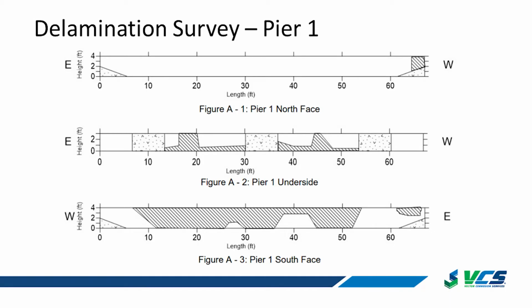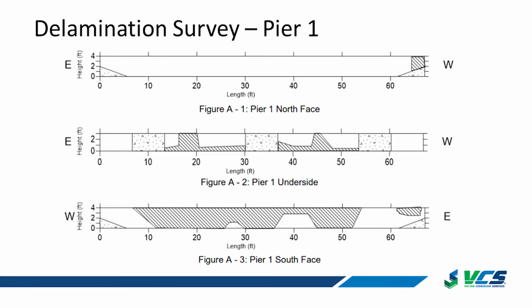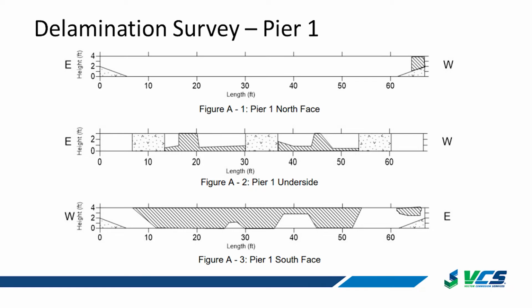We also did a delamination survey, right? That's kind of the big key here: did the system work or not? What are the current delaminations in 2020, when we were out there? Was there more delamination on Piers 1 and 2 versus 3 or 4, or was it relatively the same? And so here, this is just an example of the delamination survey from the 3 faces of Pier 1 cap. So you've got the 2 vertical faces and the underside, and the hatching is where the delaminations are on that one.